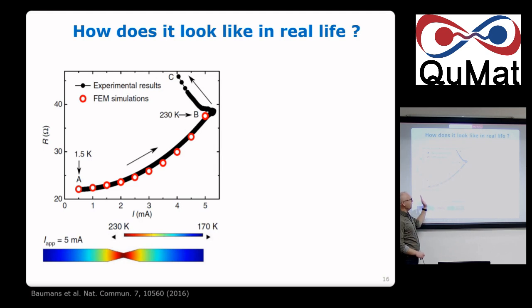So in real life, typically we can apply either voltage or current. Both. Okay. So what happens is you get to this point, and for the estimation we use just COMSOL simulation. We get an estimation. The sample is heated up to 230 Kelvin. So it's not even room temperature. Okay, we are below melting. 230 is below room temperature, and we start to electromigrate. And there you start going like so. Every time you need less and less current because the size is getting smaller. And then once we get there, we stop and we make an image of the sample.